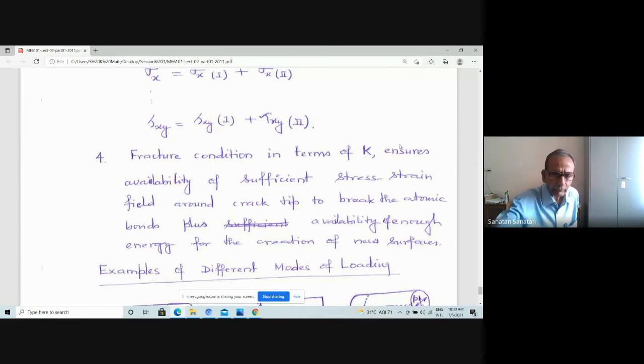And another point which has some importance: fracture conditions in terms of K ensure availability of both stress and energy conditions. I know that fracture condition in terms of K ensures availability of sufficient stress and strain field around the crack tip to break the atomic bonds, plus availability of enough energy for the creation of new surfaces. So you see that in a sense, fracture condition in terms of K is inclusive of both necessary and sufficient ones. The necessary condition is that it should have sufficient stress field and also availability of energy.